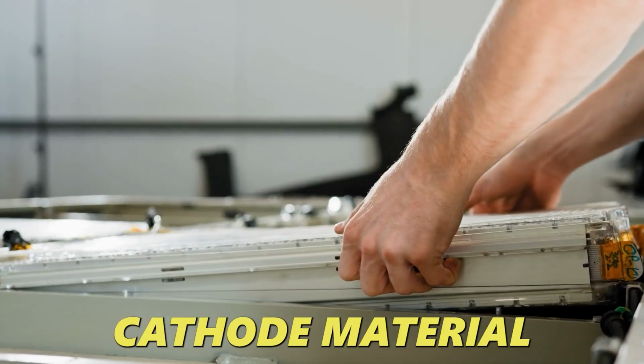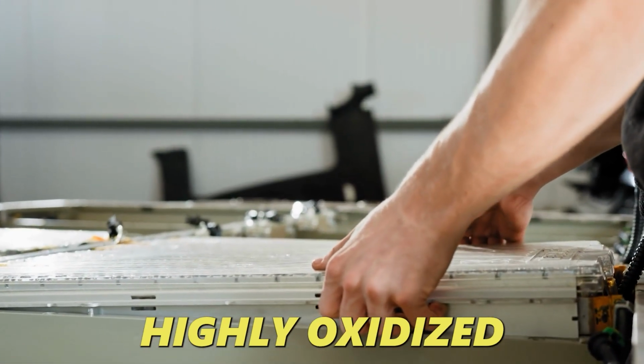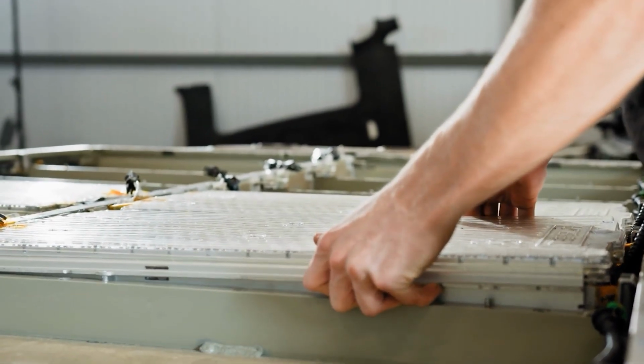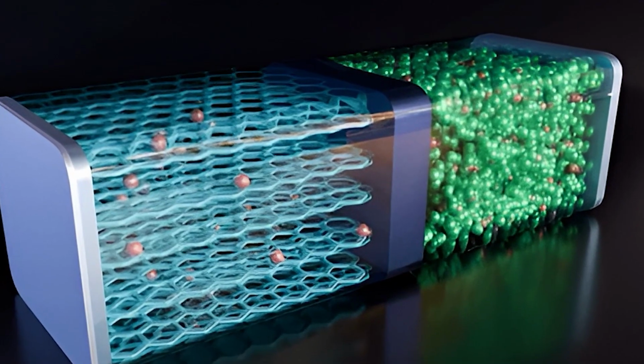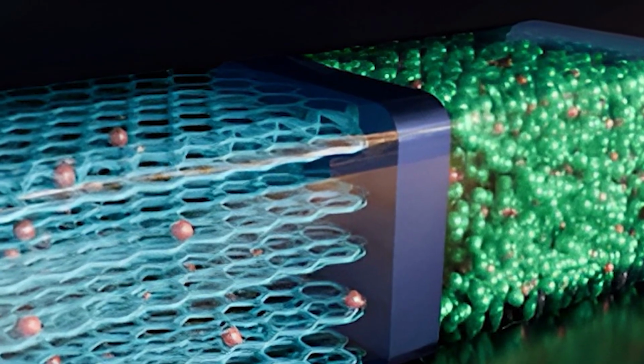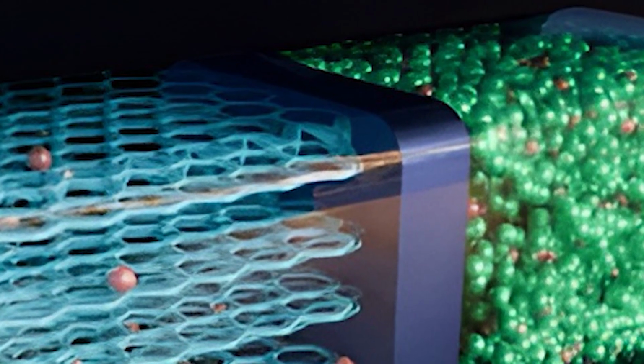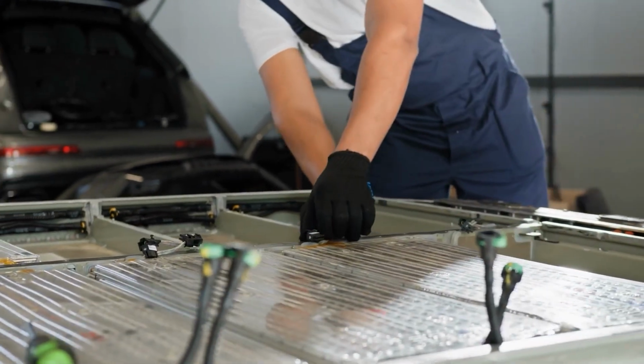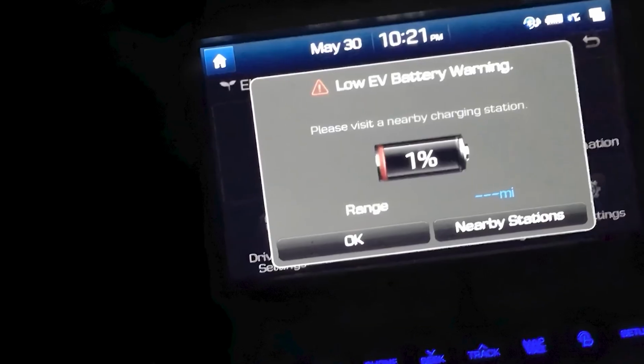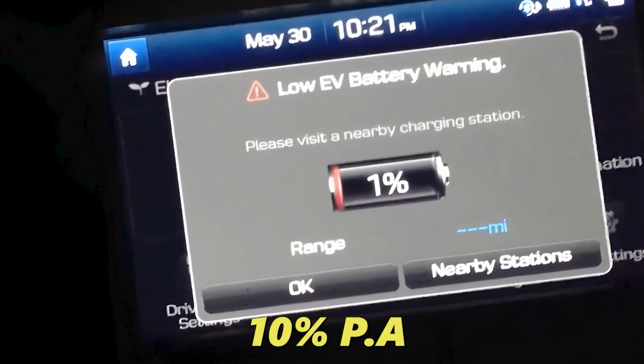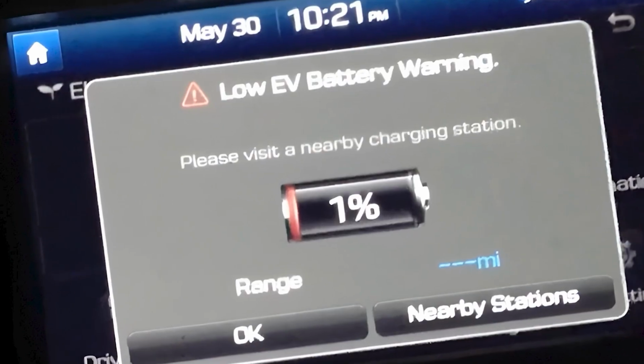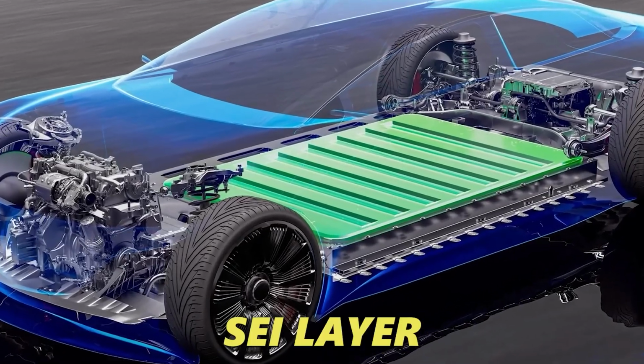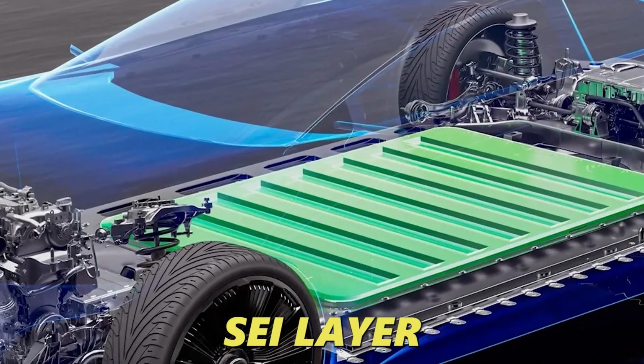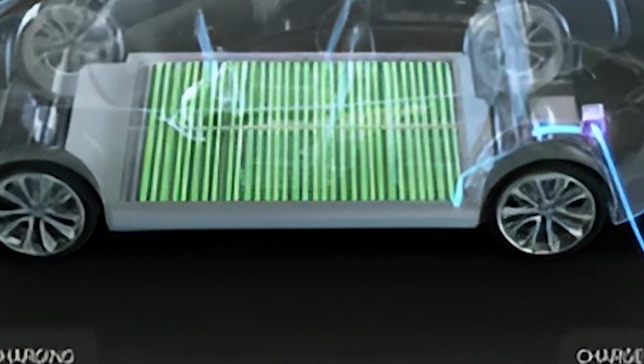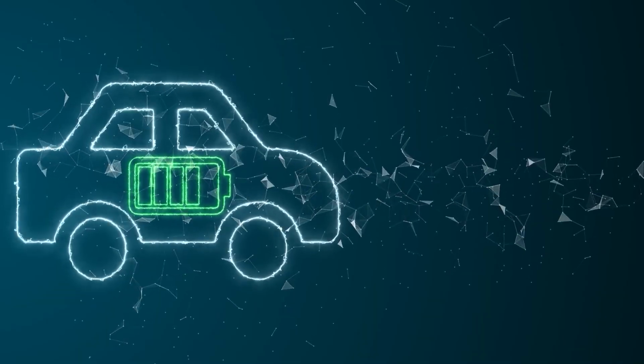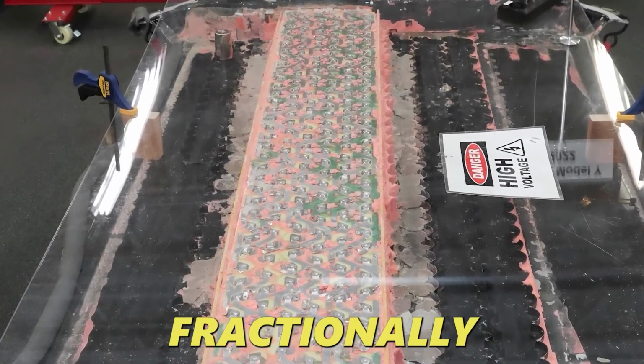Here's why. At very high states of charge, the cathode material is in a highly oxidized, chemically stressed state. It wants to react. And the electrolyte is right there, waiting to be its reaction partner. The result is a slow, continuous set of parasitic side reactions that consume both electrolyte and active cathode material permanently. Similarly, at very low states of charge, consistently draining to under 10%, the anode is under mechanical stress, and you accelerate a different set of reactions on the graphite surface that form what's called the SEI layer. Every cycle, it thickens slightly. Every cycle, it consumes a little more lithium. Every cycle, your capacity is fractionally smaller.